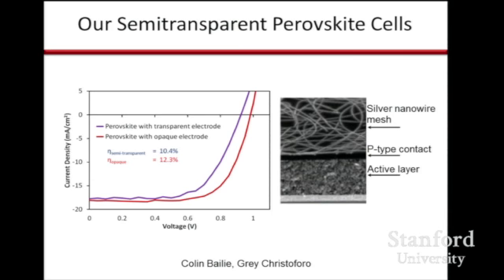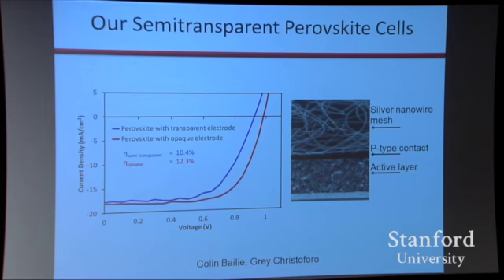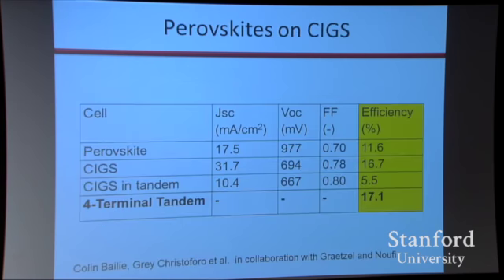This cell was made by Colin Bailie and Grey Christoforo, and just 2 hours ago they gave me better results than this. Last week, the best semi-transparent cells were 10.4%, and the special top electrode was made with a mesh of silver nanowires. These work really well, better than the conventional indium tin oxide, and we can put them down at low temperature without depositing our organic hole transporting material.